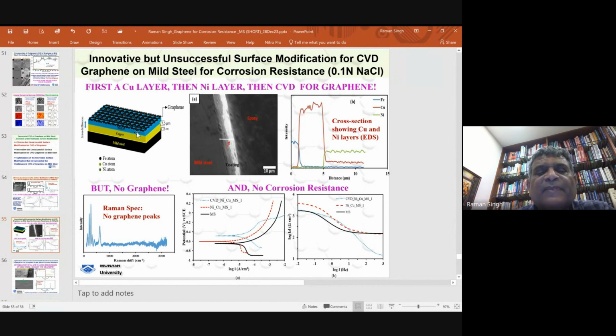We did that. Just put arbitrarily a layer of copper and a thin layer of nickel and try to develop graphene. It did not work, simply because now copper was diffusing to the nickel surface, and also mild steel was diffusing. Both iron and copper can diffuse through nickel. It was coming to the surface and it was jeopardizing the graphene development. Again, we did not have surface.